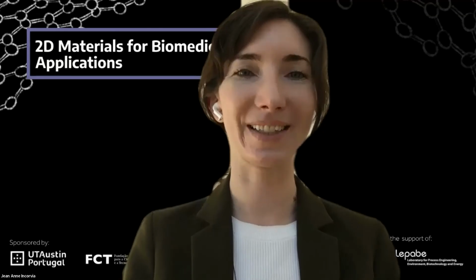MAX is not a 2D material, but MXene is, because the sheets are electrostatically bound when you remove the A atoms. You're correct. So you can do LP of MXenes to get nanosheets, but you can't do LP of MAX to get nanosheets. Similarly, he is also etching calcium silicide to take off the layers of calcium to make an electrostatically layered structure, to further do the liquid phase exfoliation to extract the sheets.